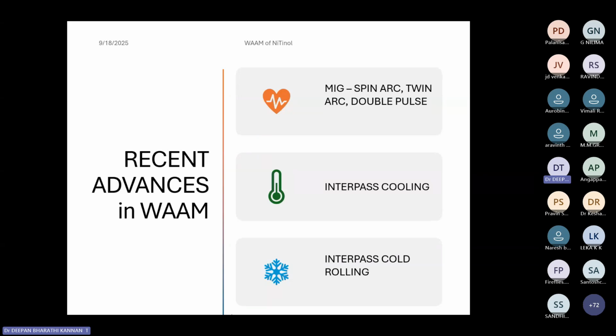And twin arc, a couple of papers are present with respect to nitinol, but still a lot of work could be done with respect to twin arc of nickel titanium shape memory alloy. And then double pulse, which is an advancement over single pulse, where we have high frequency and low frequency wave pulses superimposed over one another. Another one is interpass cooling and interpass cold rolling. These are all some of the advancements explored in other materials, which we could use for our research. I'll show you with the picture in the coming slides.